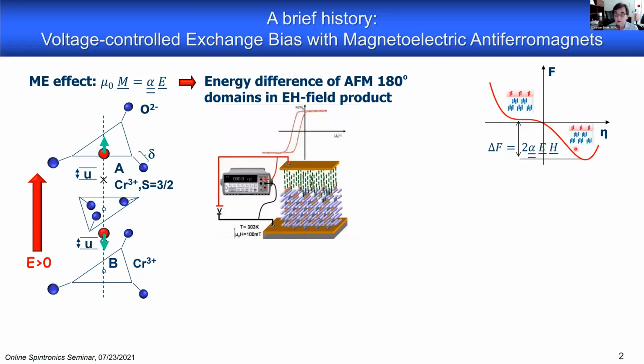So we take this now and made exchange bias systems out of these materials that are affected by an electric field. Here you see a cartoon. So we have this magnetoelectric antiferromagnet. We put here a ferromagnet on top, which couples with the antiferromagnet by a quantum mechanical exchange interaction. This ferromagnet is perpendicular anisotropic. And now by applying an electric field in the presence of a magnetic field, a stationary magnetic field, we can now switch the exchange bias from one, let's say the ordinary negative, to the positive and back.